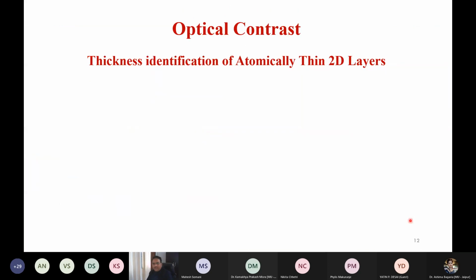And what we have done is, we understood the optical contrast method. Using that method, we have done some simulations to find out what kind of substrate you should use. Suppose you are using silicon dioxide, which is the most used substrate for device purposes also, because you have a silicon oxide layer on top of it, so you can fabricate a field effect transistor using these films.